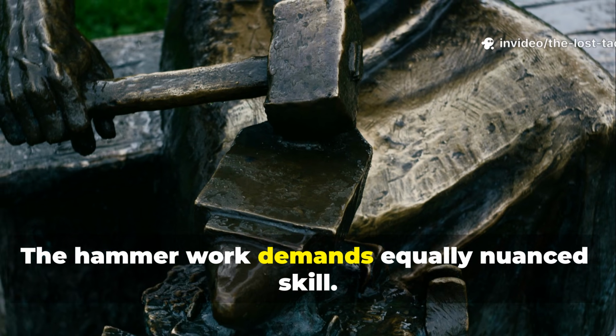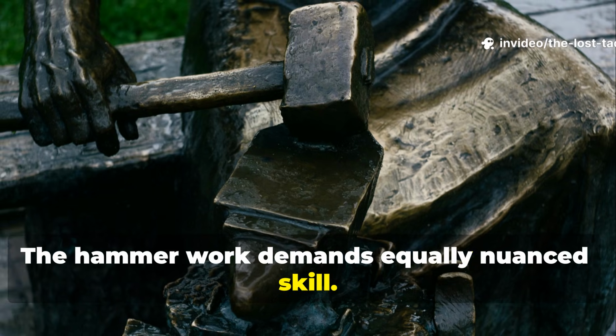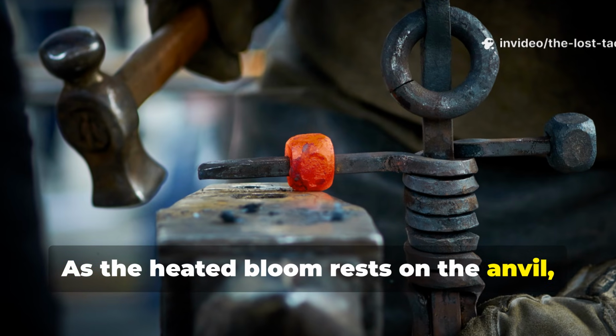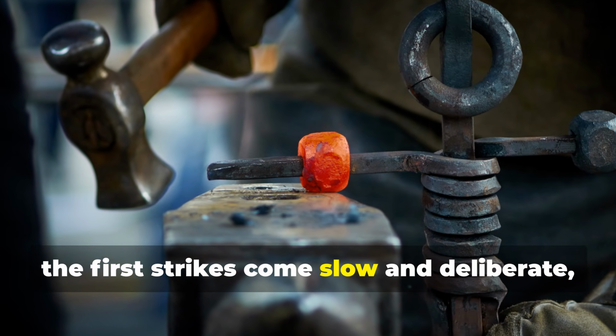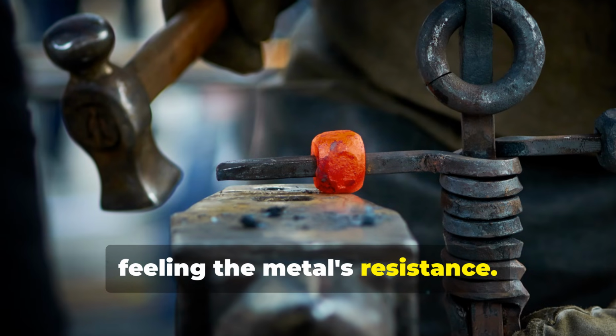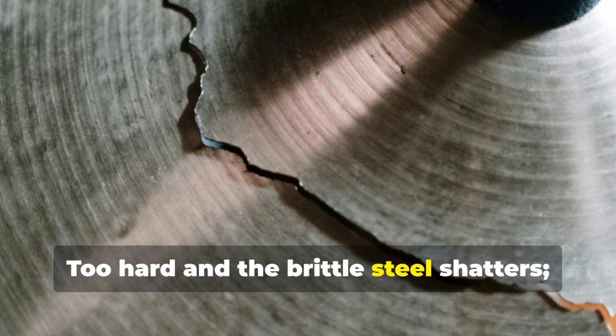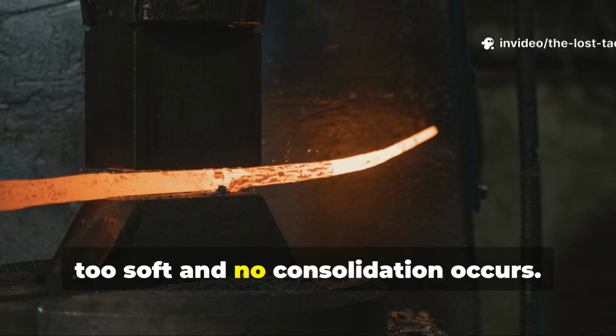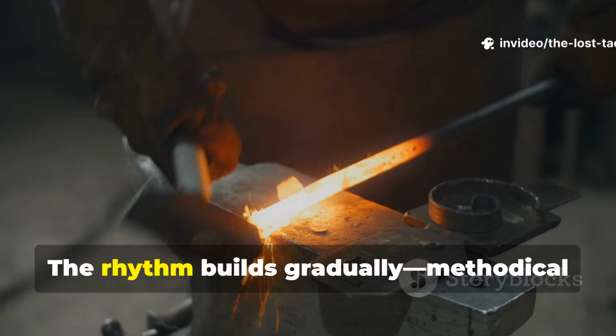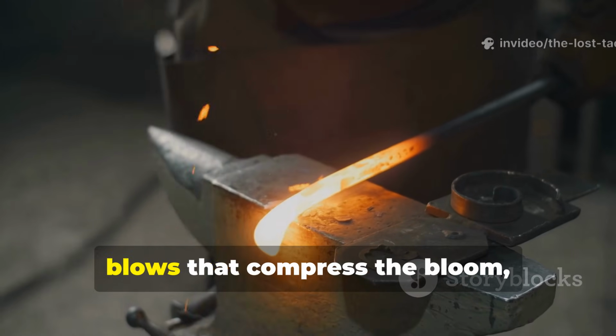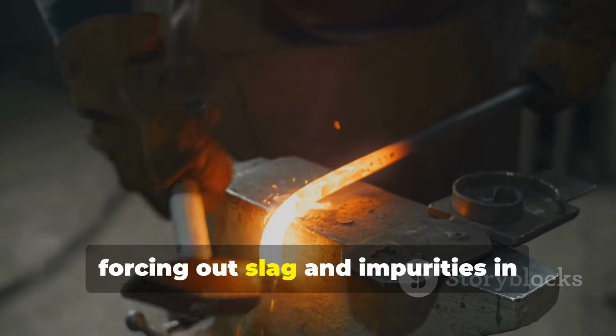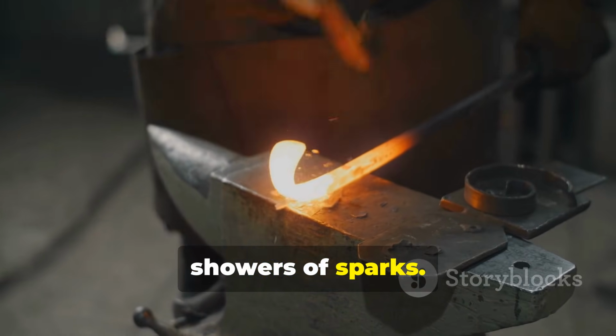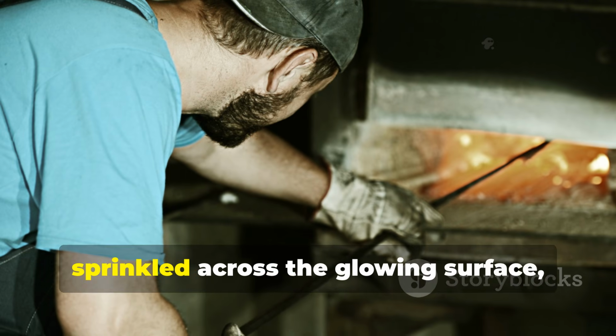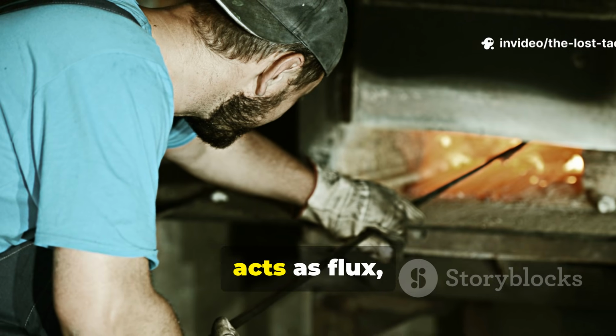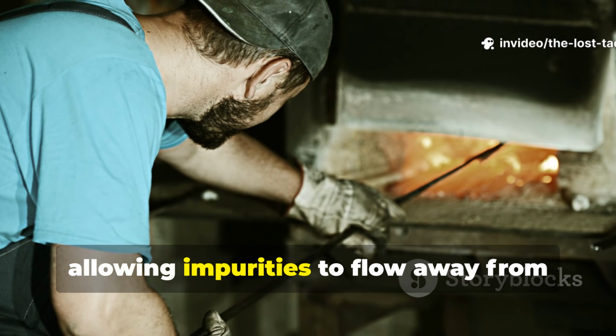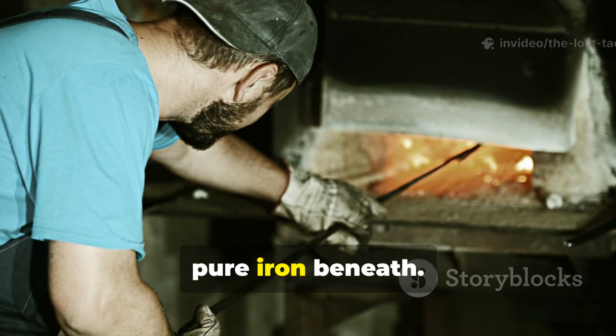The hammerwork demands equally nuanced skill. As the heated bloom rests on the anvil, the first strikes come slow and deliberate, feeling the metal's resistance. Too hard and the brittle steel shatters. Too soft and no consolidation occurs. The rhythm builds gradually, methodical blows that compress the bloom, forcing out slag and impurities in showers of sparks. Rice straw ash, sprinkled across the glowing surface, acts as flux, allowing impurities to flow away from pure iron beneath.